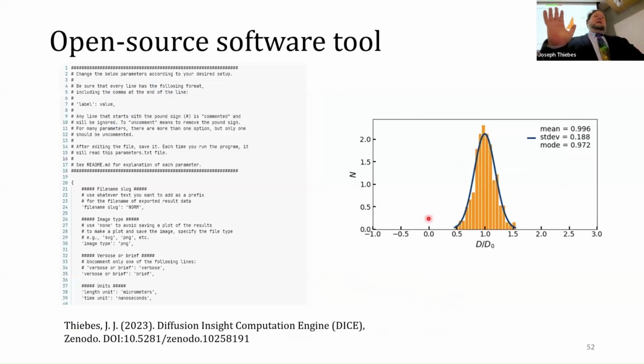But because every researcher has a different situation, different instrumentation, different contrast to noise, different reasons for doing what they're doing and different levels of tolerance for imprecision, I created this software tool which basically does the simulations that I was doing for this study. People can put in their own parameters and run it. It gives them this result, which shows the fitted diffusion coefficients and how far they are from the nominal value. And it gives you the mean, standard deviation, and mode, so you can see if there's skew, if there's bias. This is open source, so people can improve it, use things other than Gaussian fits or diffusion models that are not linear. And there's some folks using it.